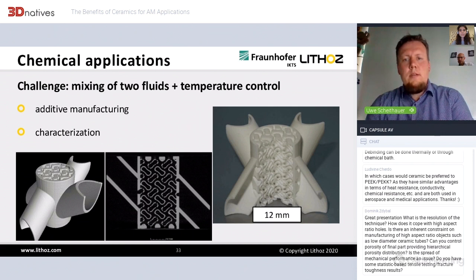The outer diameter of the inner cylinder is about 12 millimeters in the sintered state. And here on the left, you see some pictures from our computer tomograph, which shows that also the small holes in the walls between the different fluidic systems are open, and we could realize a very nice resolution inside the component.